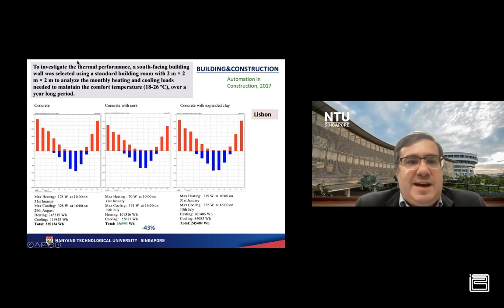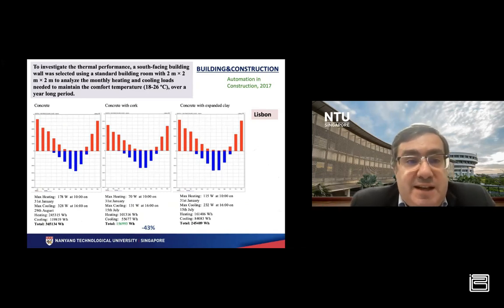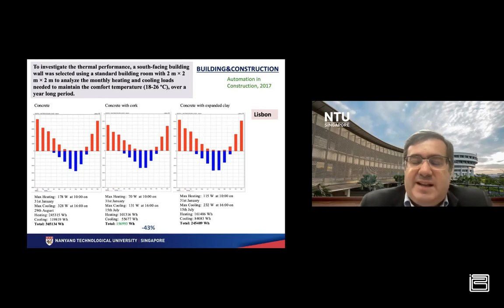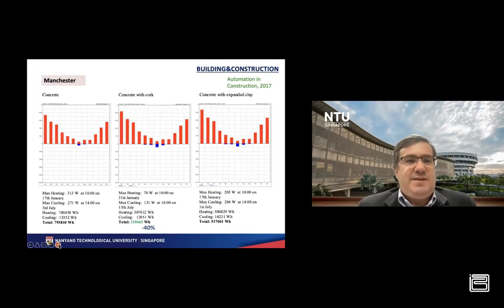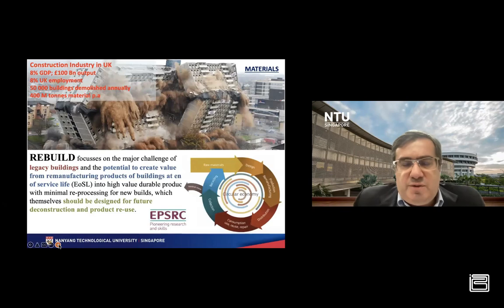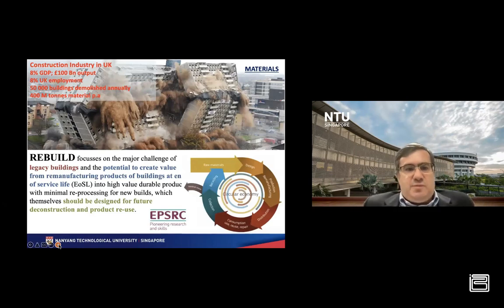by using a combination of concrete and cork, it is possible to reduce by more than 43% the energy consumption to keep the temperature more or less constant. While in the case of Manchester, the use of concrete and cork allowed us again to reduce the energy consumption by around 40%. Finally, and I'm not going to give too much detail because we are still finalizing this project.